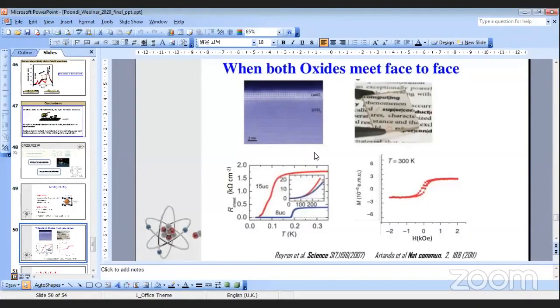Interface. On strontium titanate, on a single crystal, you will have one layer of titanium oxide over a strontium oxide layer. In charge terms, this is neutral. You will have strontium 2 plus and oxygen 2 minus, titanium 4 plus and oxygen 2 minus. So this is charge neutral.